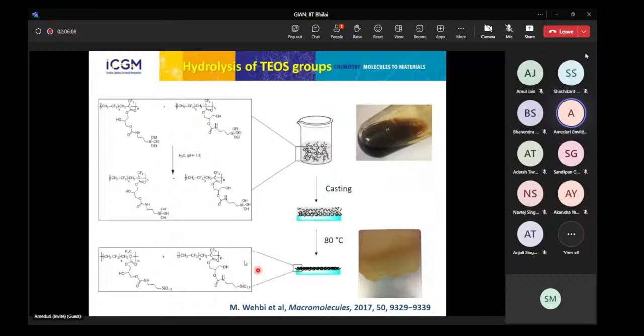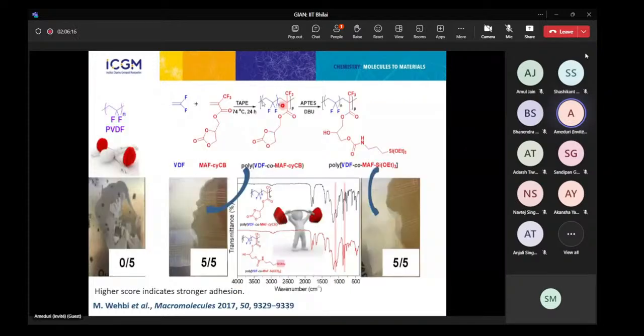So you have here a system in which you make a coating directly on the plaques, and what we observe, these copolymers could be very efficient with a scratch test. Okay, you make a scratch, and then with a test with Scotch tape, you try to remove the squares that you have built with a scalpel. And in this case, you have a mark 5/5, which is the maximum, very good adhesion.